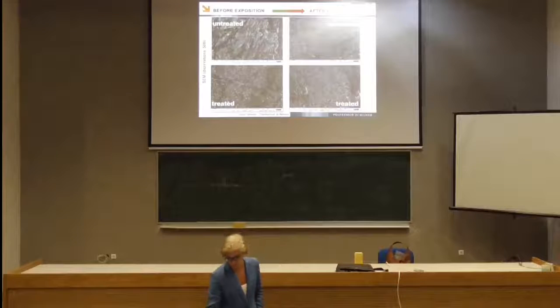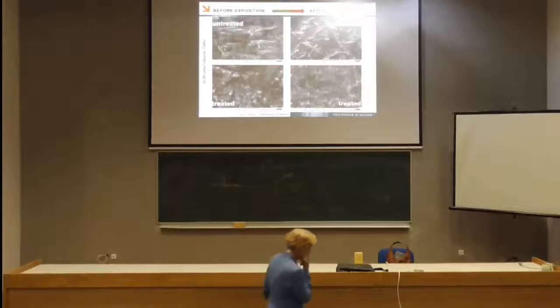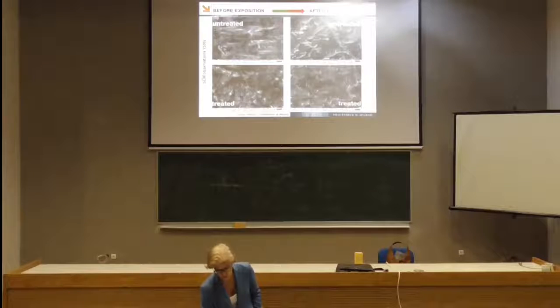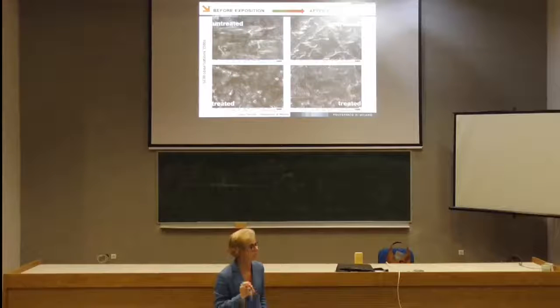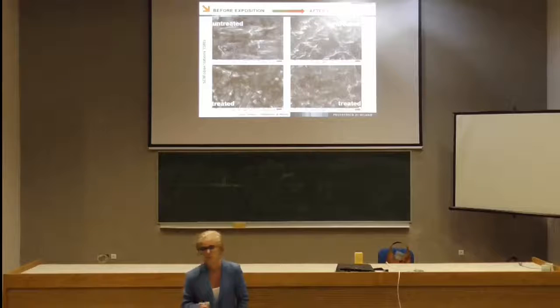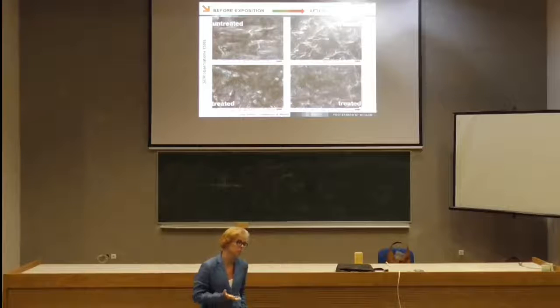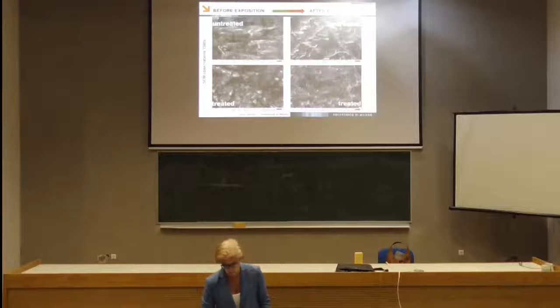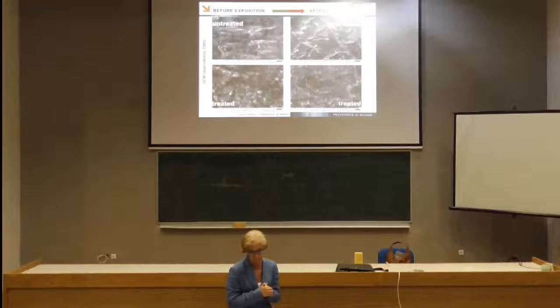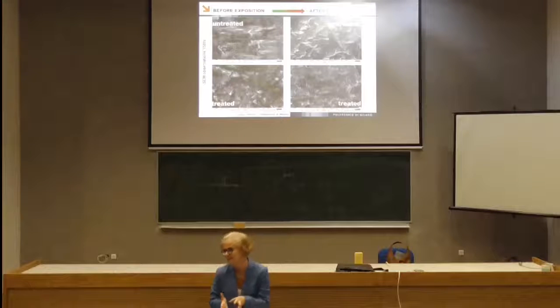And this is true when we observe the surface with a scanning electron microscope. It's very easy to see that on the treated surface, after exposition, we see these micro fissures, geometric micro fissures that open in the coating, and this is because it was in very extreme condition. And of course, with these micro fractures, water can go inside and enter the material.